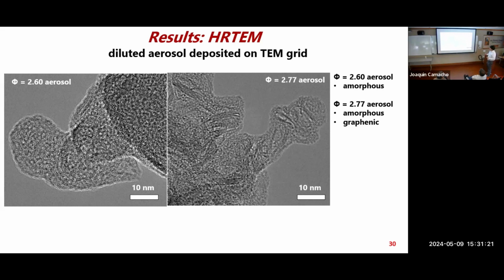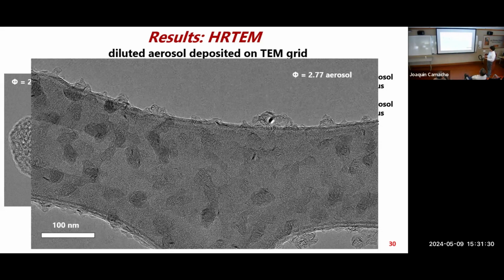So that's an example of the TEM images under this diluted aerosol sample. And here's even more evidence that this is clearly not soot. Soot would not be as transparent. These are very small graphene clusters or graphene sheets. And this particular sample collection method is relatively transparent. The contrast is not great because it's so thin, few layer graphene. Of course, graphene is one layer. You have single layer, two layer, and then few layer. So this is graphene of a few layers, not more than 10 or so. Very transparent, not soot.